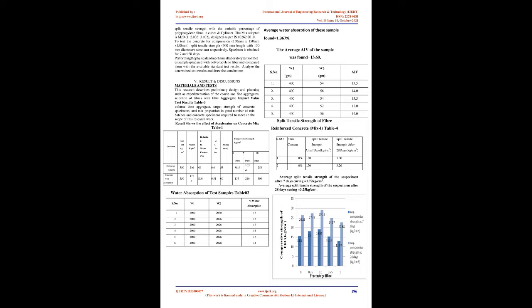66.7%. However, the compressive, splitting tensile and flexural strengths were weakened significantly when PPF was over 0.3% VF in hybrid fiber reinforcement, total content of 1% VF. The strain field shown in digital image correlation images suggests that hybrid RTSF and PPF can create a synergistic effect in restraining the crack growth and the post-cracking behavior of concrete, especially toughness that was enhanced with the presence of PPF. RTSF was more effective in restraining shrinkage of concrete than PPF. With the increase of PPF content in hybrid fiber reinforcement, the chloride migration coefficient of concrete was reduced by 4.9%, 6.8% as compared with the mixture reinforced with only RTSF.